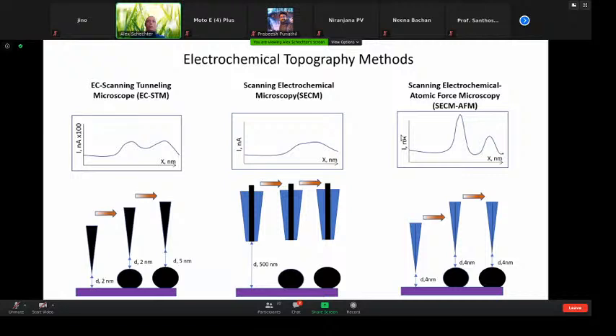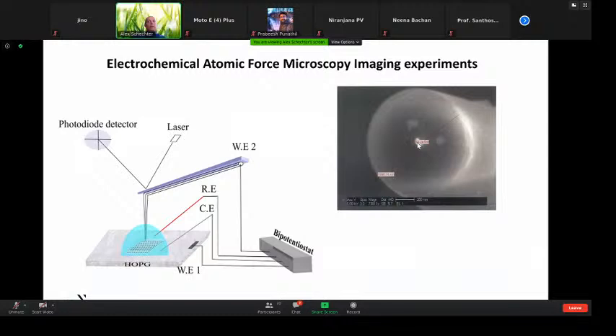So here is an image of a tip. The inside, this is the platinum wire embedded in silicon. The diameter is around here of the platinum. We set up an interesting setup. We just took the electrode and the catalyst, put it on an HOPG. We have a laser, we have a photodiode, we have the electrochemical cell. The dots down here are the platinum particles or the catalyst particles. Everything is connected to a potentiostat, and we have a reference electrode and counter electrode to complete the electrochemical cell.